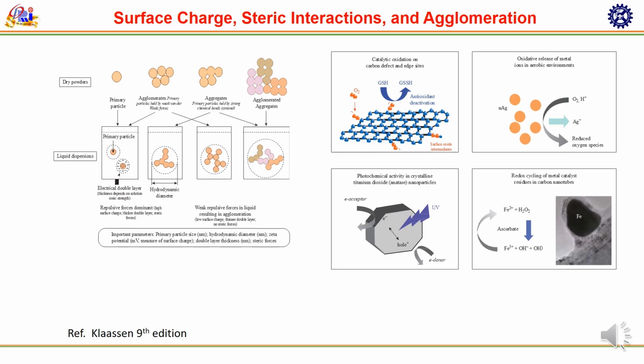So, you can see in this slide, nanoparticles do not exist as isolated entities; they interact with the surroundings, leading to aggregation and stabilization. Surface charge, zeta potential, steric interaction, and chemical reactivity dictate stability in biological fluid, uptake by cells, and toxic potential through ROS generation, ion release, and catalytic activity. This explains why two nanoparticles of the same composition but different modification can have different toxicological outcomes.